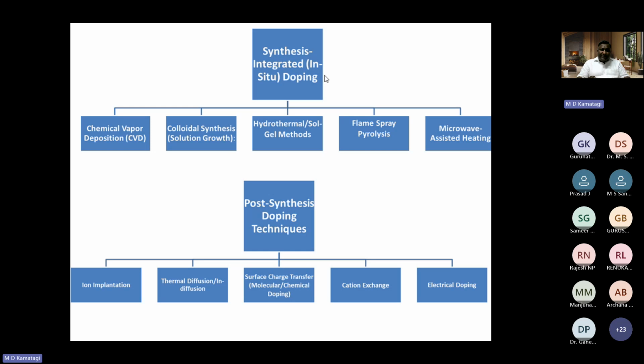Another very cost-effective method is colloidal synthesis, or solution growth, which is widely used for quantum dots and nanoparticles. Dopant precursors are added to the host precursor solution. The reaction temperature and timing of dopant injections are critical for successful incorporation of the dopants.